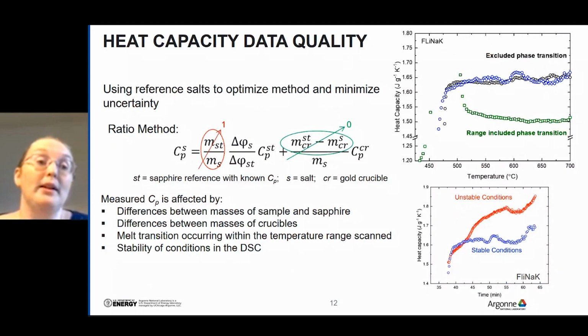For heat capacity data quality, we've made some great strides forward this year. The basic method is that we use a reference material, a sapphire, and we do a comparative ratio method. So we measure 2 empty cells to establish baseline. We measure an empty cell versus the sapphire to get the delta phi ST here, and then we measure an empty cell and our sample to get the delta phi S. And through this equation, we're able to get the heat capacity of the sample.